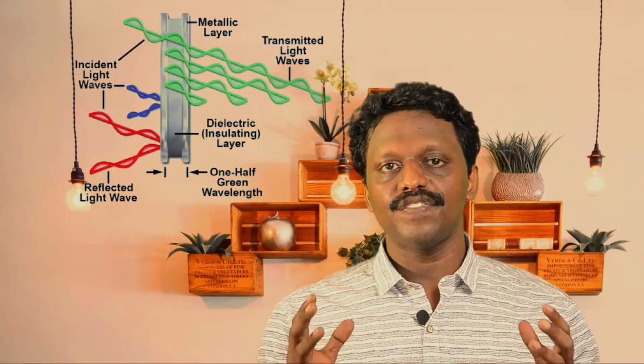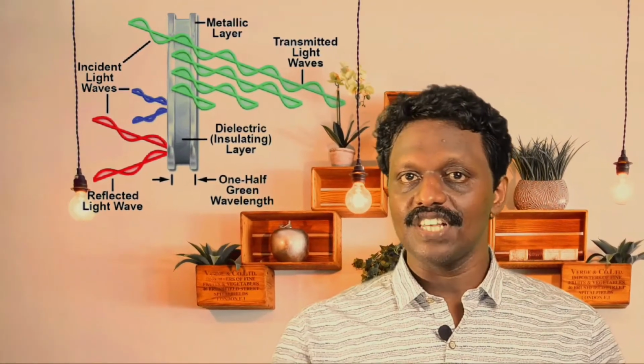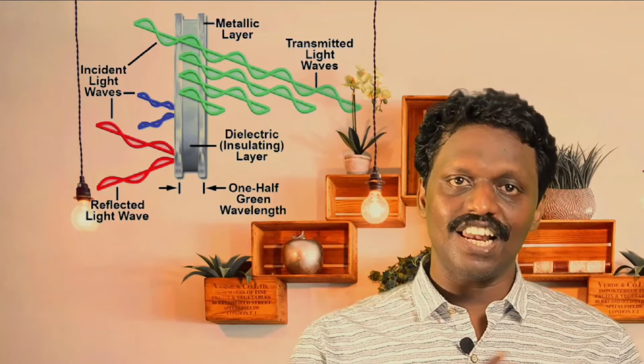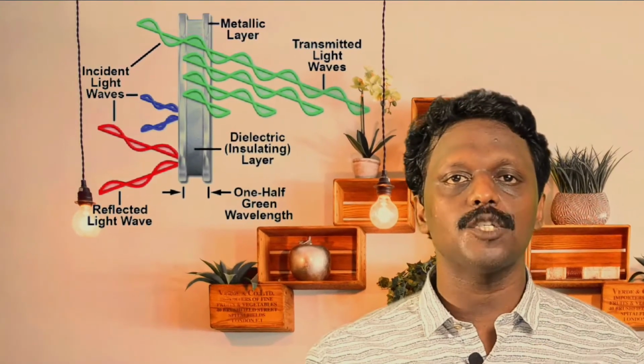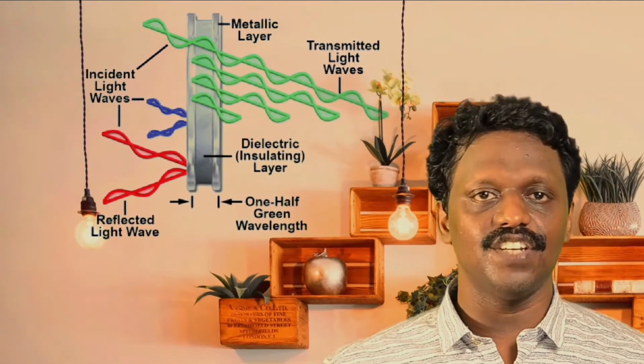In general, interference filters are constructed of planar optical glass coated with dielectric materials in layers either 1/2 or 1/4 wavelength thick, which act by selectively blocking and reinforcing the transmission of specific wavelength bands through a combination of constructive and destructive interference. The filters are designed to transmit a limited range of wavelengths that are reinforced through constructive interference between the transmitted and reflected light waves. Wavelengths not selected by the filter do not reinforce each other and are removed by destructive interference or reflected away from the filter.